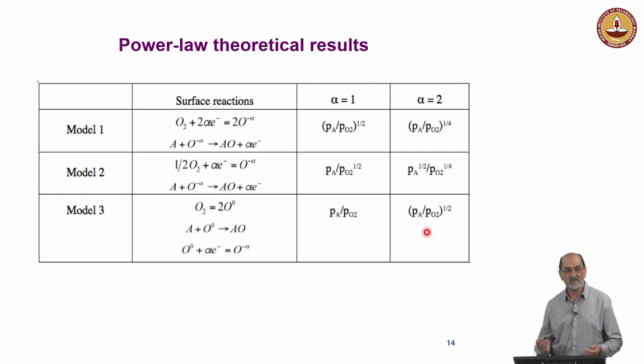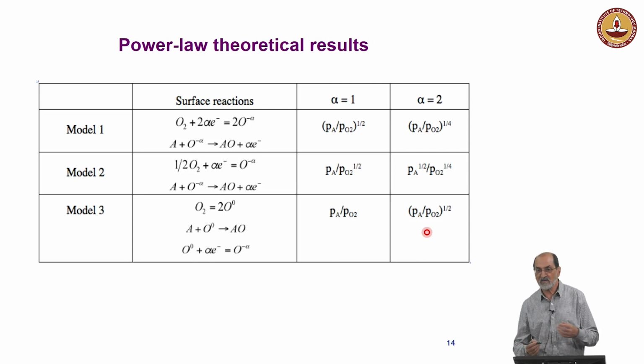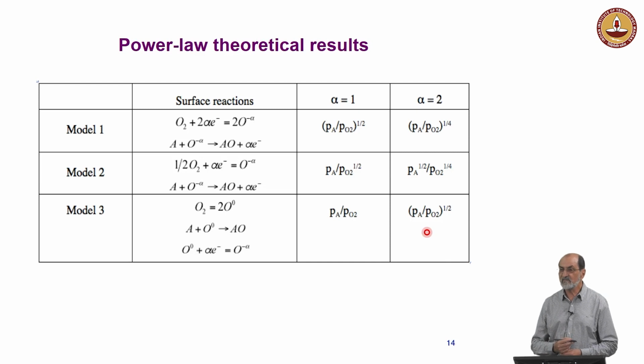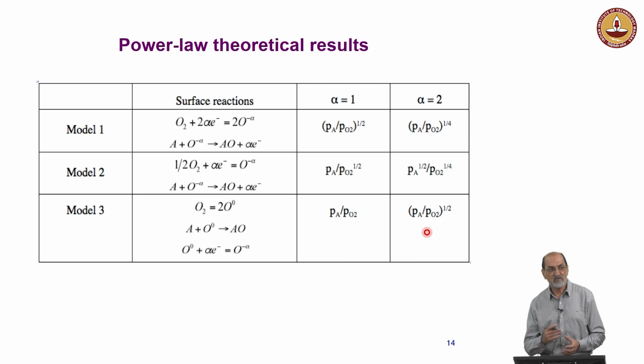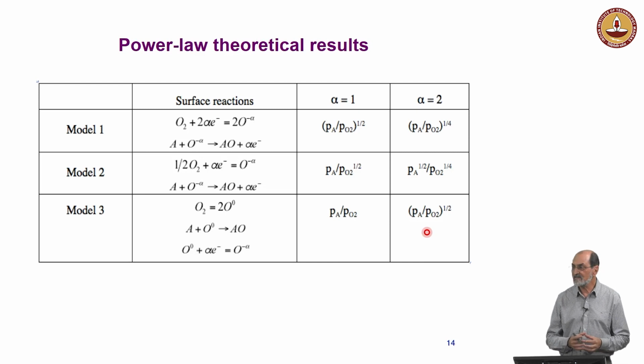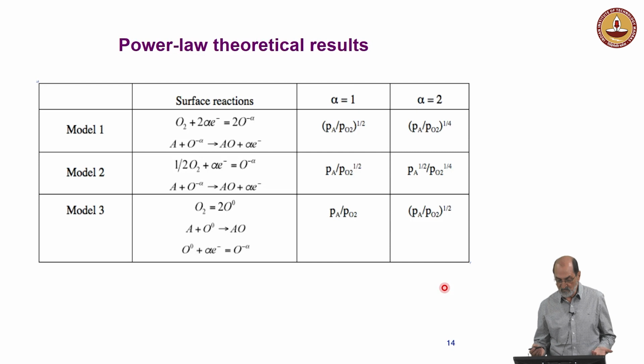This is very spread in the literature. There are many papers, and they apply sometimes one model, sometimes the other model. And essentially, they found very different results. The experimental results show a lot of dispersion. I think the dispersion is because they are using large or medium-sized grains, in such a way that the conduction involves the tunneling current. Since the tunneling current depends on many details, and sometimes the grain can be partially depleted or completely depleted if we have a medium-sized grain, they found any kind of results. But we are going to make the experiments with very small grains, where this can be directly applied, because in that case, the conductivity is directly related to the electron density. So we are going to make the experiments to check which one is correct, or apparently which one works.